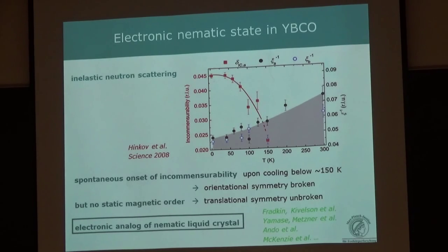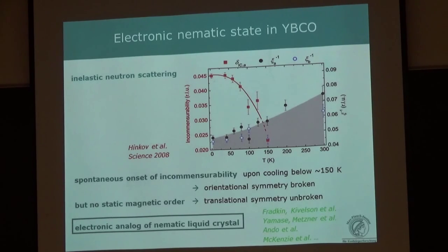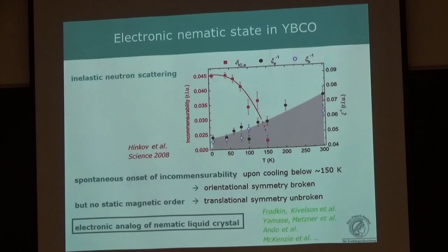Regarding whether the crossover is equally sharp in the quasi-elastic regime: over the entire temperature range where the incommensurate order exists, the incommensurability is temperature-independent. It's the same incommensurability in the inelastic and quasi-elastic spectra. Around 8% doping, the low-energy spin fluctuations disappear and you see a gap in the spin fluctuations forming. The spin fluctuation onset temperature for the nematic order goes up slightly from about 150 K to about 200 K as you go from 6% to lower dopings.